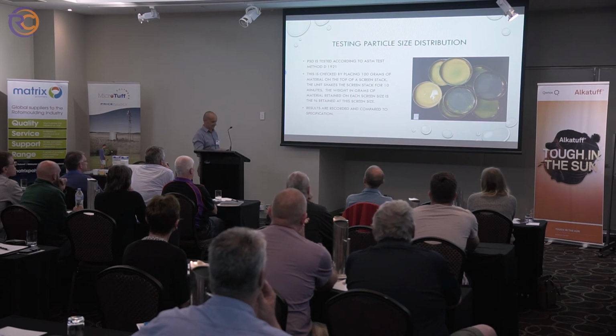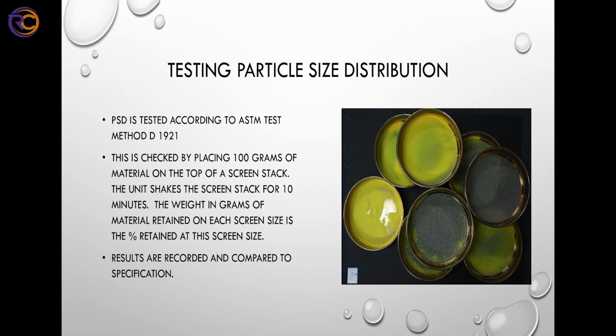And as you can see here, you've got several different sieves, and then you have a pan at the bottom, and we measure what is retained in that pan, because this powder and probably the next screen up are the ones that can contribute to issues in the moulding process, and we don't want a lot of those fines in there for reasons we just talked about. So the results during the process are recorded and compared to specification, and if we see any issues we can adjust either the screens or the gap or whatever we need to do to get back on spec.